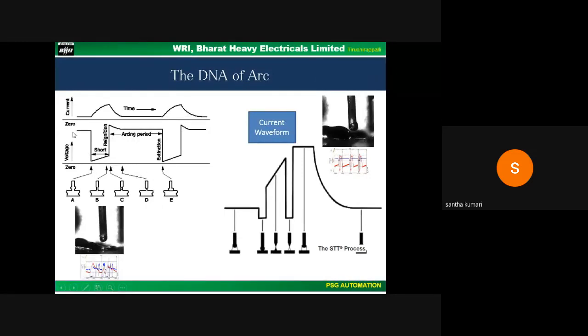You can see here the conventional short circuit: the current ramps up from the base current, the droplet forms, and it gets dropped on the weld pool, and then again it continues. Whereas in the new waveform control power sources, they reduce the current initially to avoid premature droplet formation, and they reduce the current again before the droplet transfer to avoid spatter. In this way, the inverter-based waveform control power sources have been developed to suit different applications in thin sheet joining, root pass application, and also cladding applications.